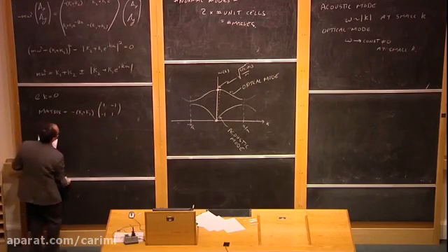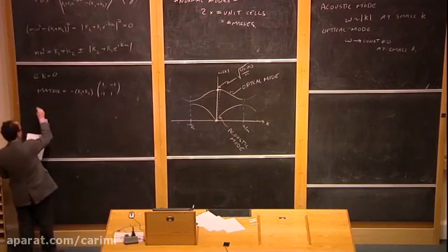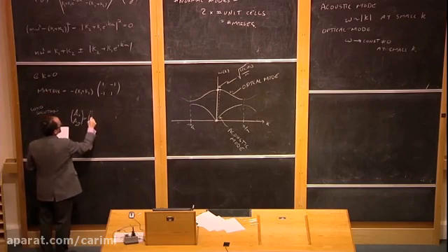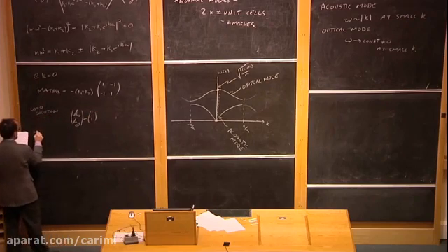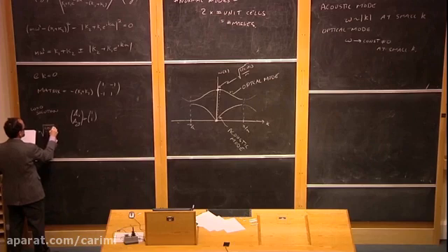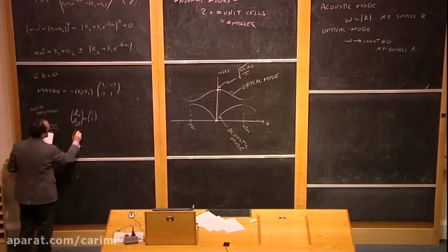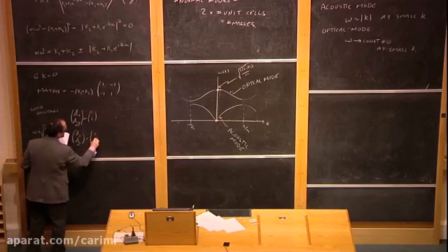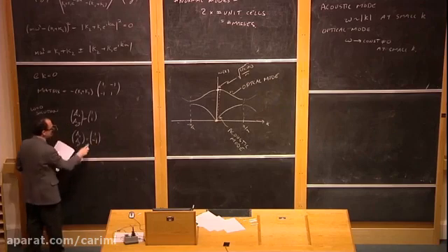So the eigenvectors, we have two possible eigenvectors. One is for the omega equals 0 solution. We have an eigenvector ax, ay equals 1, 1. Whereas for the optical mode solution, the other eigenvector, the high energy, high frequency eigenvector, we have ax, ay equals 1, minus 1. So what is this telling us?